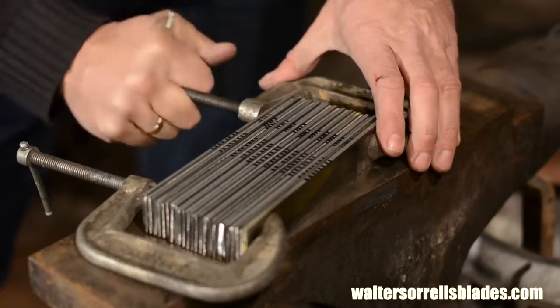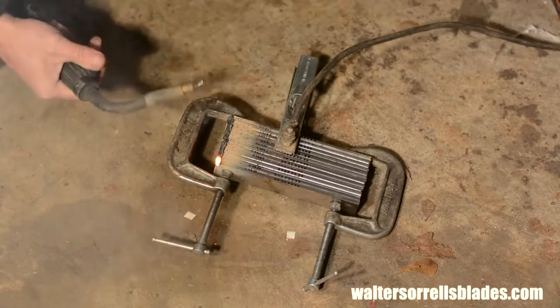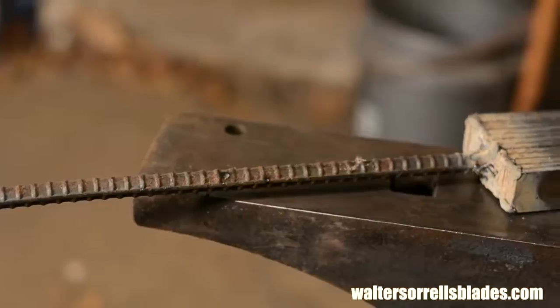Then I'll clamp them together and tack weld them together with my MIG welder. If you don't have a MIG welder, you can wire them together with iron wire. If you do that, you'll need to use a thick piece of stock on the bottom, say 1/4 of an inch thick, as a handle. I'm going to weld up each corner, running a bead right straight down each corner. Then I'll weld on a handle.